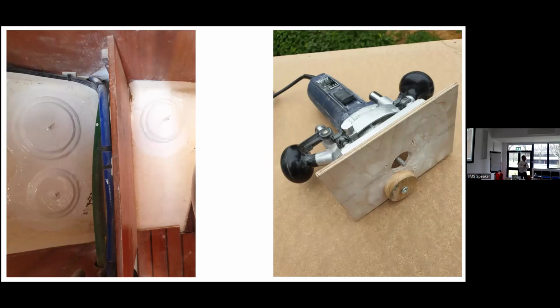It will cure against something inert, and that's the trick. It's inert. Anybody that's seen a failure of a gel-coated epoxy repair has probably seen that the epoxy hasn't cured sufficiently. So we always talk about 48 hours for a DIYer, but an overnight cure, 24 hours for a yard with infrared lamps, is sufficient. We actually say 7 days in our literature for a full cure.